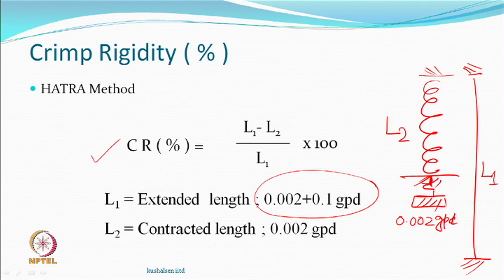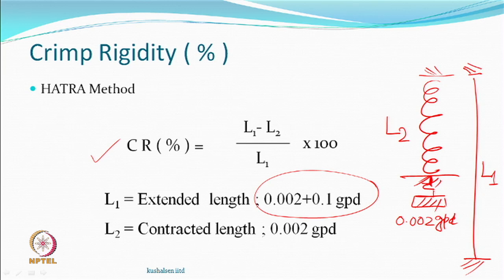You see very small stress, right. What it means is that, how do you measure? So, this standardization is that full extension is not an issue. If you have a load of just 0.1 grams per denier, all the crimps are gone, and theoretically you may have extended up to 300%,